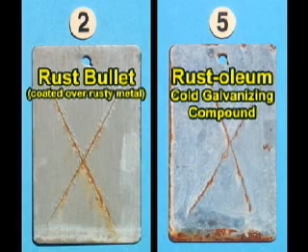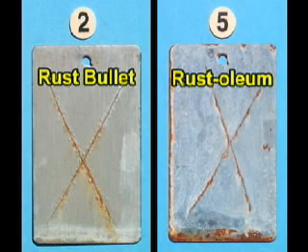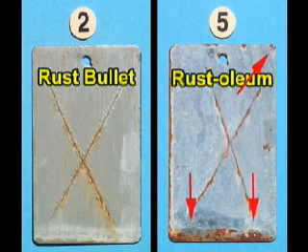This panel is coated with Rust-Oleum cold galvanizing compound. This does provide a higher degree of protection than the others. Zinc particles are providing a degree of galvanic protection. But as you can see by the corners and the bottom of this panel, it has almost no abrasion resistance, and the resin washout will accelerate the process of decay.